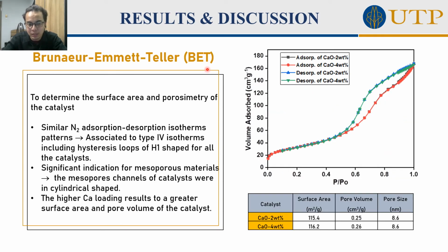So the next one is BET. Basically, BET analysis is used to determine the surface area and also the porosity of the catalyst. This is the BET pattern that we obtained from the lab, and from here we can analyze the similar nitrogen adsorption desorption isotherm pattern, which is associated with type 4 isotherms including a hysteresis loop, which is this one, a hysteresis loop of H1 shape for all the catalysts. We can see a similar hysteresis loop for both CaO 2% and 4%. This is a significant indication of a mesoporous material, meaning the mesoporous channels of the catalyst are cylindrical in shape, and the higher Ca loading results in a greater surface area and pore volume of the catalyst.